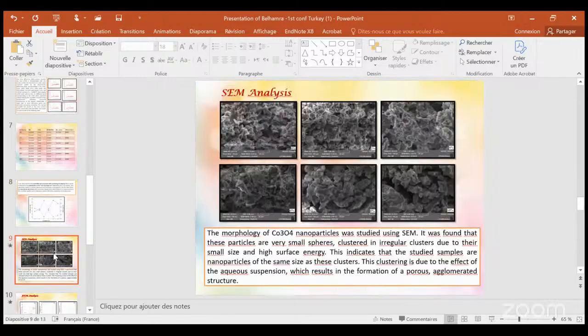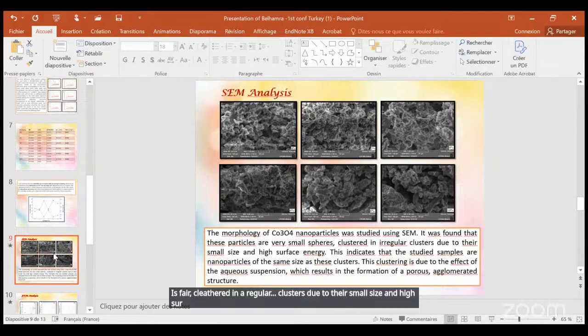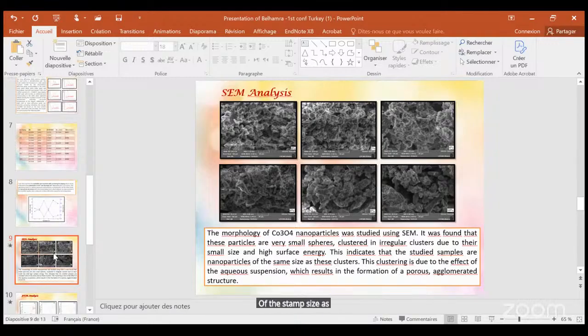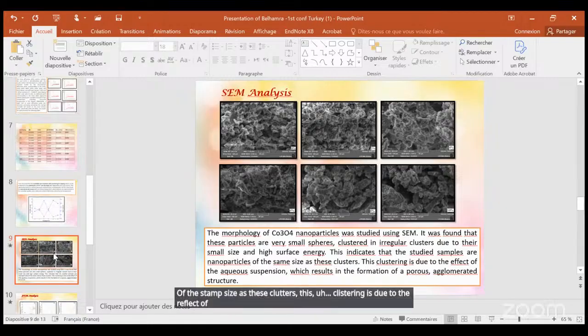As for the morphological analysis, the morphology of Co3O4 nanoparticles was studied using SEM. It was found that these particles are very small spheres clustered in irregular clusters due to their small size and high surface energy. This indicates that the studied samples are nanoparticles of the same size as these clusters. Clustering is due to the effect of the aqueous suspension, which results in the formation of agglomerated structures.